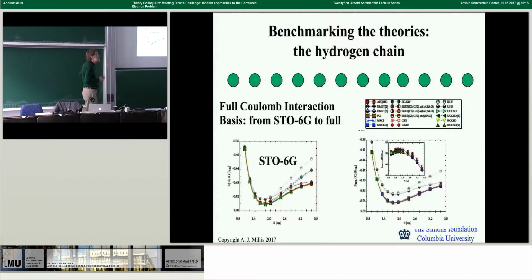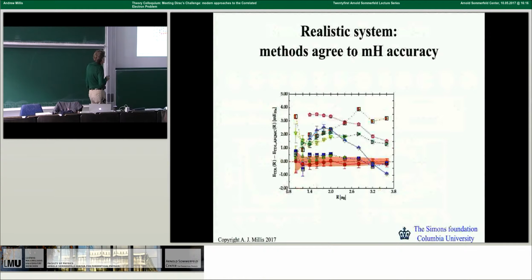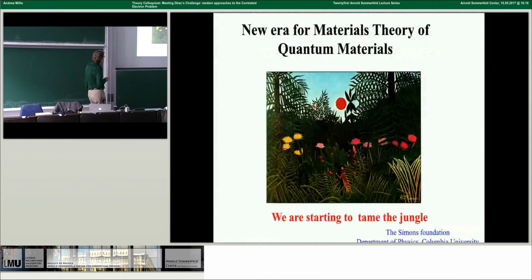So doing this forces us to come to grips with two of the key issues of real materials. First, the full matrix elements of the Coulomb interaction, and second, the realistic structure of the full basis that you need to deal with problems in the continuum limit. And what you find after a certain amount of optimization is that, again, there are a wide variety of methods which now all get essentially the same answer to within a milli-Hartree. That's these numbers.